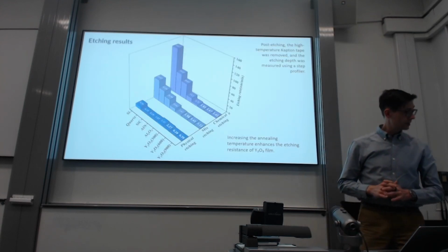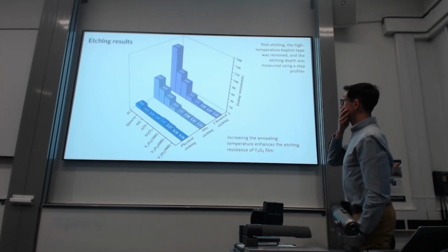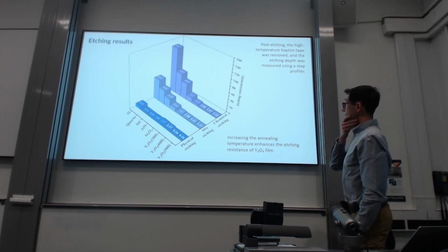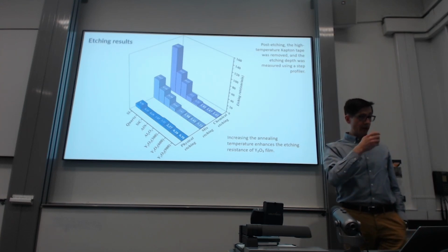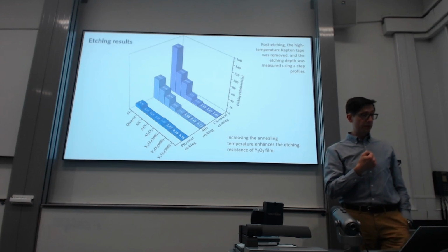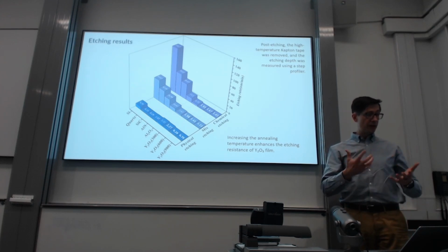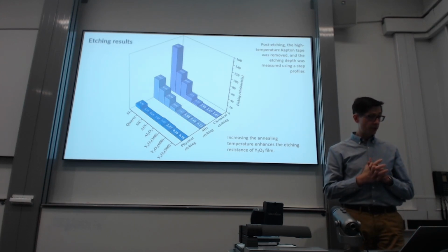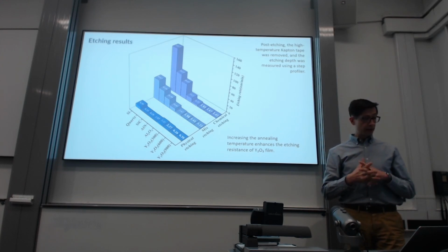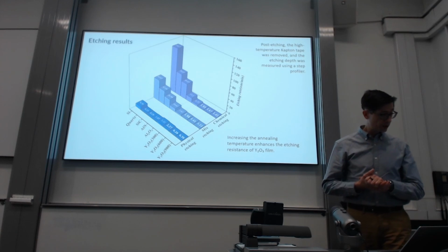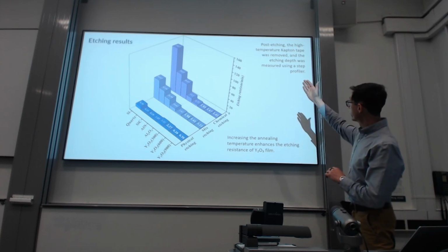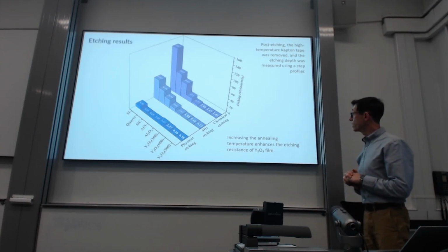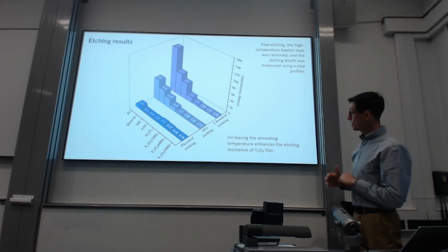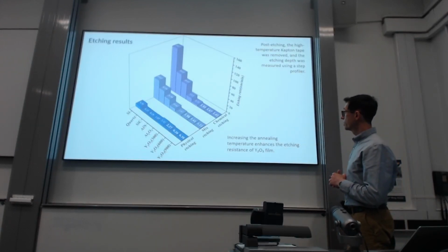So these are results for the etching process. After the etching process, we removed the high temperature Kapton tape to reveal that edge, which was then measured using a step profiler, so that we can establish the depth of etching achieved, and with that we were able to calculate the etching rate. So you can see the three variants of the coating for two different annealing temperatures, for